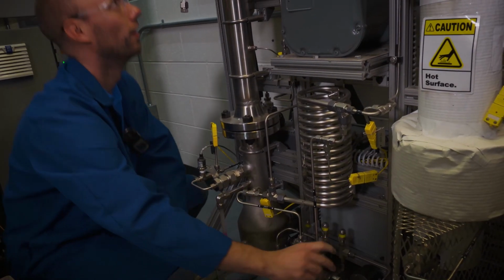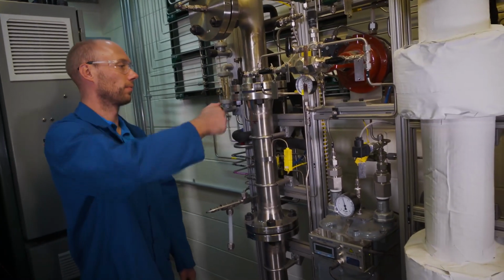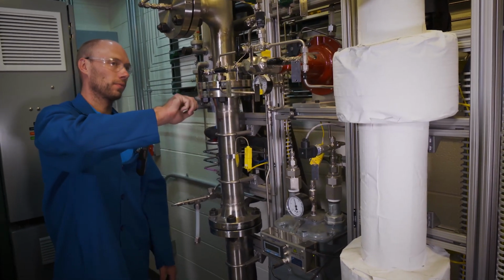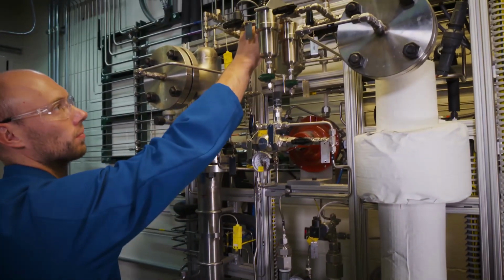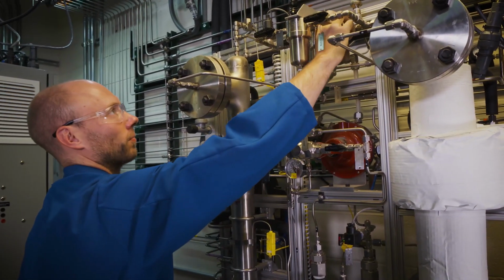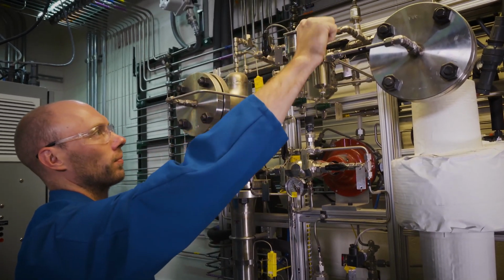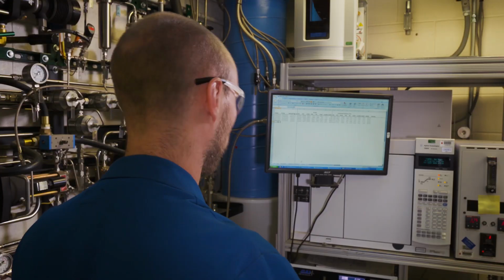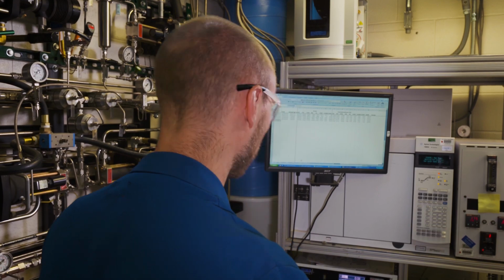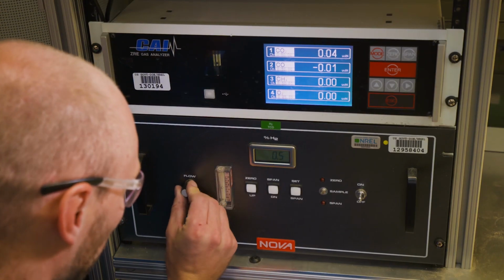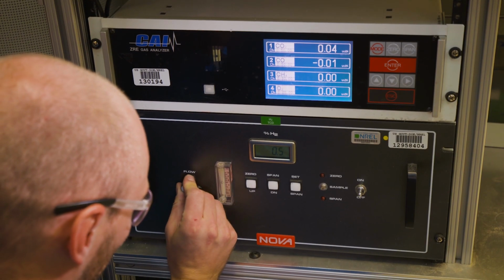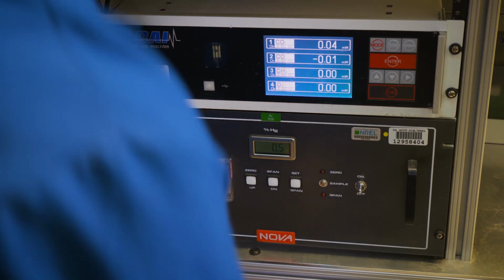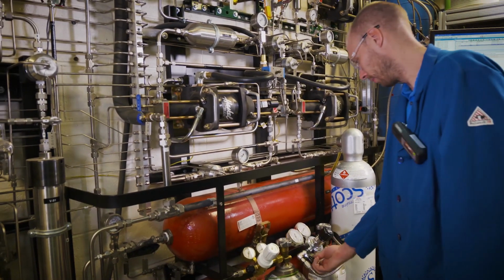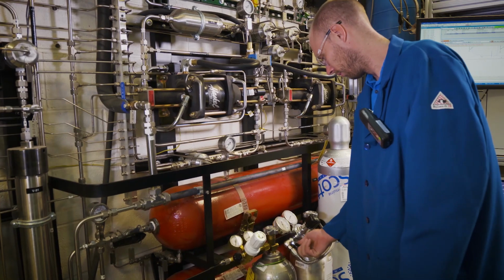Catalyst regeneration requirements can constitute a significant portion of the final cost of fuels or chemicals. Consequently, we've learned that it's important to begin investigating effective regeneration procedures early in the catalyst development cycle. We've used a number of operando methods to investigate the deactivation modes of metal carbide catalysts during reaction and treatments to regenerate the active carbide structure as quickly as possible under conditions as close to those used during reaction as possible.